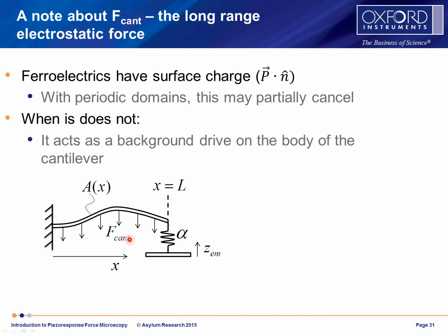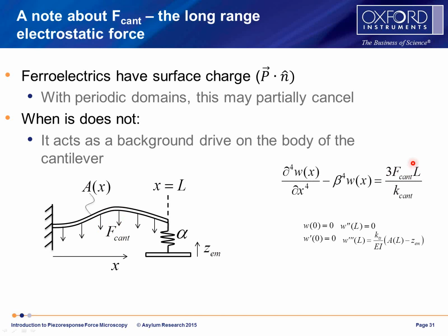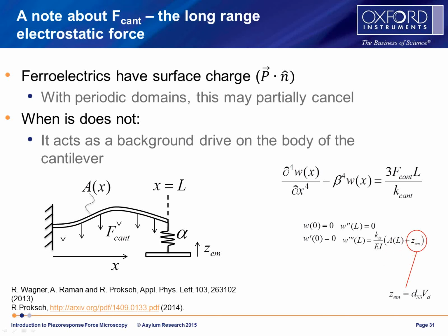We denote that as this F cant, and this is in the model that I showed before. If we bring that up here, it's that term in the cantilever, and that is something that at least in the PPLN sample, in the results I'm going to show you on the next page, was actually required to get good agreement between the experimental and theoretical values. I should also note in this equation that the piezo response, that Z electromechanical, comes in as a boundary condition in that equation. So you can read a little bit about it in these articles, both the spectrograms and some of the specific measurements that I'm showing here.